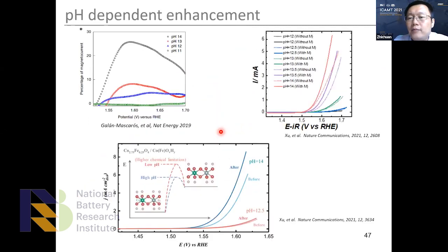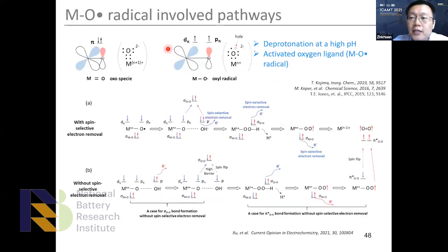And so the secret, I would say, is over here, which is an important phenomenon, that is a pH-dependent enhancement, because we can only observe an increment under the magnetic field at a high pH value, not at a low pH value. Okay, this is not a universal phenomenon for all the catalysts, of course, not for all pH values. So this is an important radical because at a high pH value, we know that the OH will undergo a deprotonation process and give us an activated oxygen ligand, which can be expressed here as metal oxygen radical.